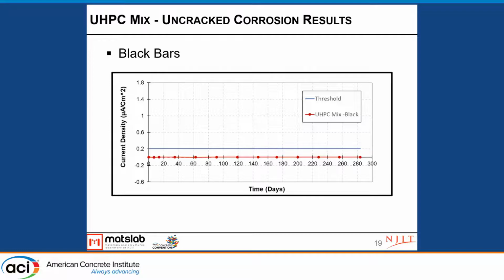It's going to be 1 year soon. The blue line shows a threshold for the corrosion current, and the red line is the measurements for the UHPC. For now, everything is 0. As soon as you see some kind of corrosion, the red line jumps up and passes the threshold level. It means that you have some electrochemical reaction between anode and cathode, which potentially can be corrosion. It's too soon for these materials to see corrosion, probably taking years. I also have some specimens, for example UHPC with epoxy coated rebar, that probably take 10 years to see some kind of corrosion, if you see any.